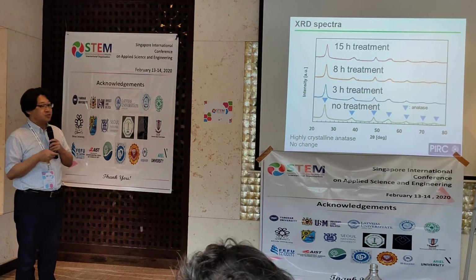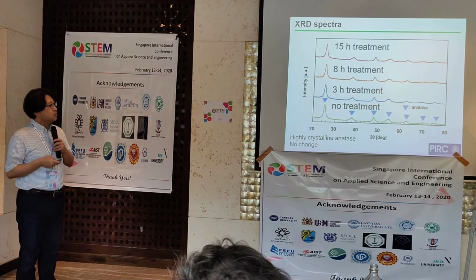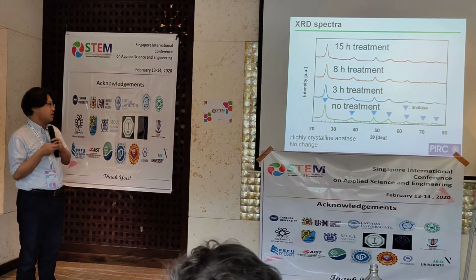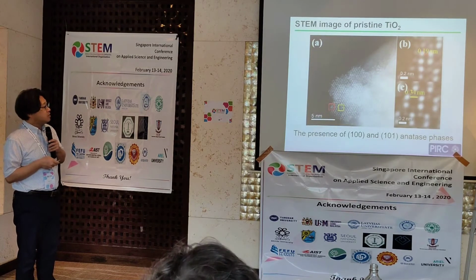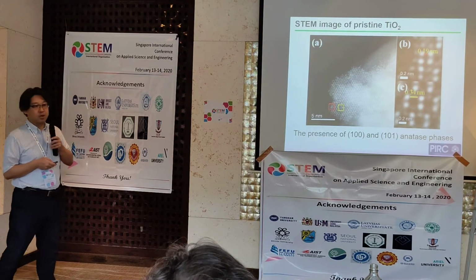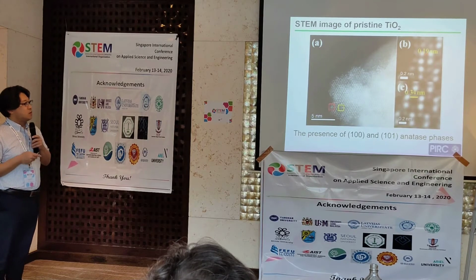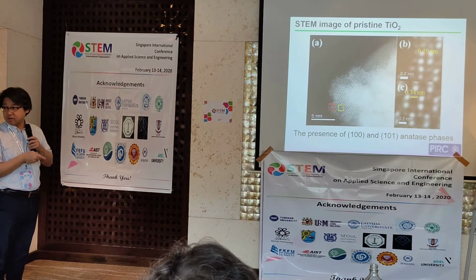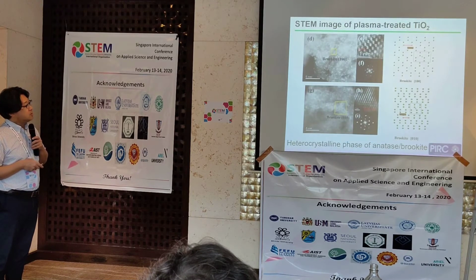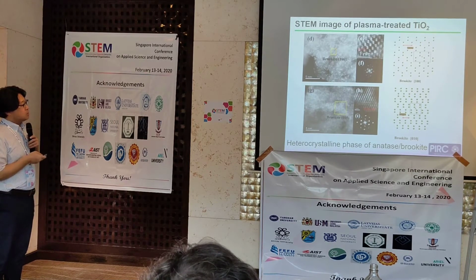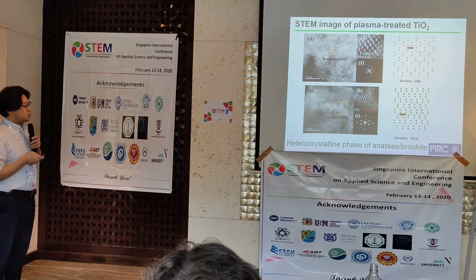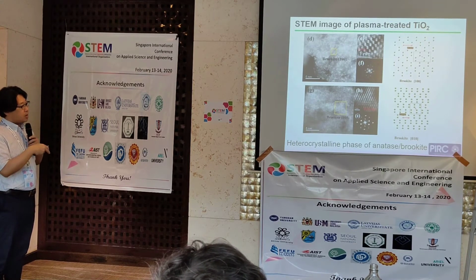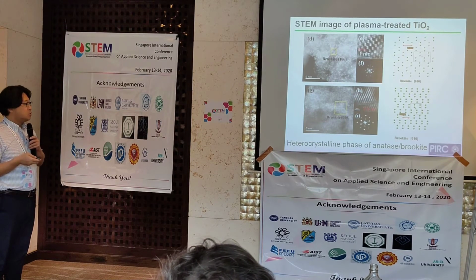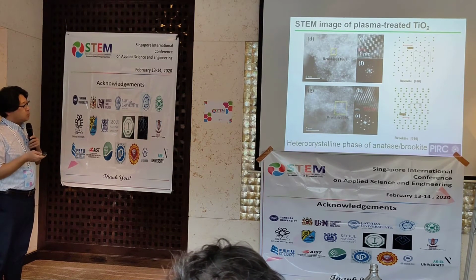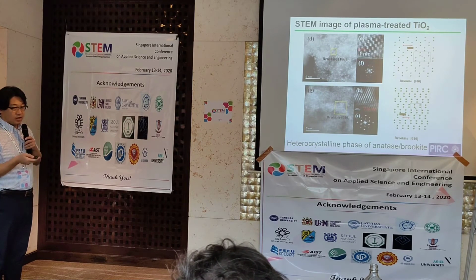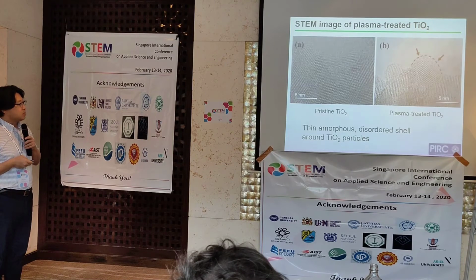So this is the X-ray spectra check, and after plasma treatment, there is no change in the starting anatase crystal. Then this is the STEM image of pristine TiO2. So we check the 100 and 101 anatase phase. This is the starting material. Then this is after plasma treatment. So partially brookite structure appears among this anatase structure. So we make a heterocrystalline phase of anatase and brookite under this plasma treatment.